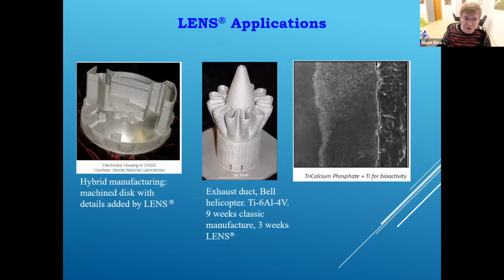Some other examples. You can see on the left-hand side what we call hybrid manufacturing. What they say is hybrid in this case is that they are actually using the base. The base is made of stainless steel, and they are just adding features locally by printing. The bottom part was manufactured by machining. Sometimes people use the term hybrid this way, not to be confused with hybrid when we combine additive with subtractive. The Bell helicopter you saw earlier is a qualified part. And then on the right-hand side, you can see the bioceramic coating, calcium phosphate, that was processed by DED.